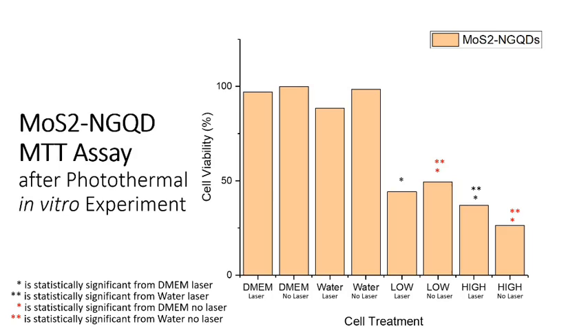For molybdenum disulfide, we see the same with the high, that there is significance between the water and the DMEM. We also have to remember how toxic the molybdenum disulfide was originally. With the low concentration and the no laser treatment, we do see a difference between the water and the DMEM, which tells us that this was still a relatively toxic sample. And then in the low, we only see a difference between the DMEM and not the water. So that's telling us that if there was any photothermal effect, we couldn't totally attribute it to the molybdenum disulfide NGQDs, that part of it is due to the water in the solution.